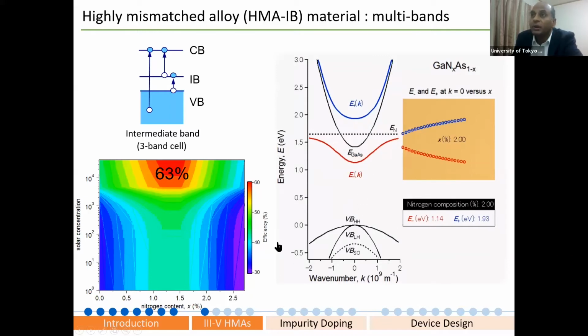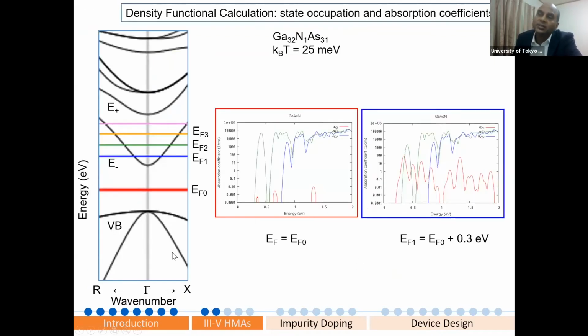And the maximum band gaps will show you 63% conversion efficiency. But for a single junction solar cell, I already told you the limit is 31%, okay? So making intermediate multiple band gaps gives you the opportunity to break the single junction limit. Okay, let me go next. This is a DFT calculation, density functional theory calculation. If you put a little amount of nitrogen in gallium arsenide, I show you here that we have multiple band gaps. And here I show that we can play with the absorption coefficient between the triple bands, and how you play with the Fermi levels. I'm not going into details, but I want to show you that playing with the Fermi level is one important technology to improve the two-photon absorption.